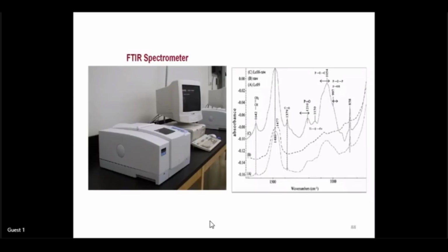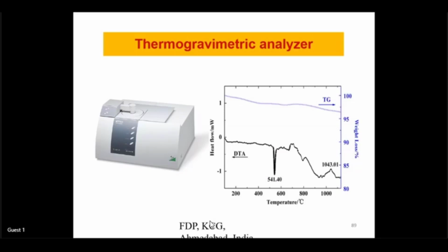So FTIR is a very crude measurement. It gives the stretching and vibrations, and in ferrites we check whether two bands are formed; then you can say the ferrite is formed. Different materials require different characterization, and they basically give the stretching vibrations of the chemical bonds. Fine. So TGA will decide whether endothermic or exothermic reactions occur. On the left hand side, the thermogravimetric analyzer is there, very small in size. You can keep it on your table. It decides heat flow and melting point, and how much loss there is of the final product, that is known as weight loss.